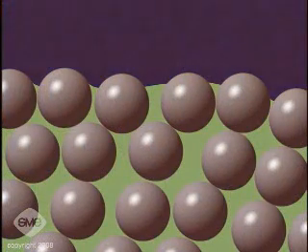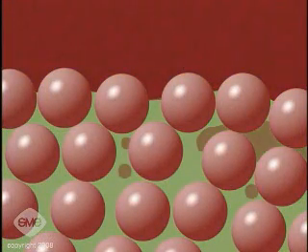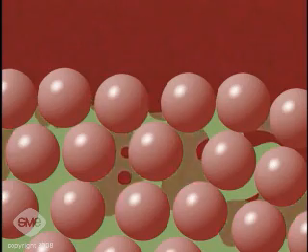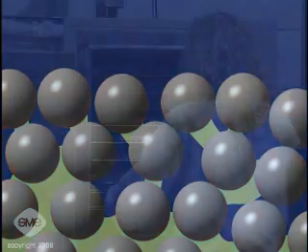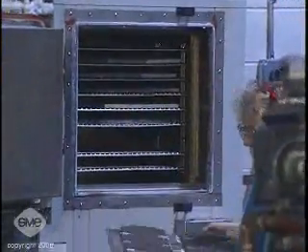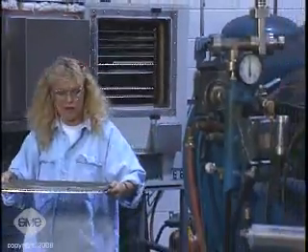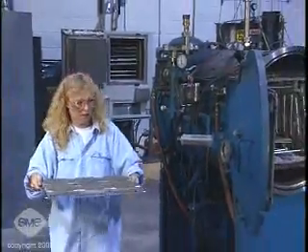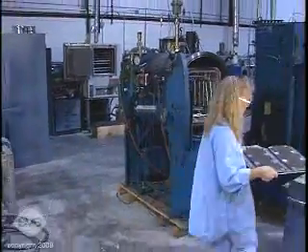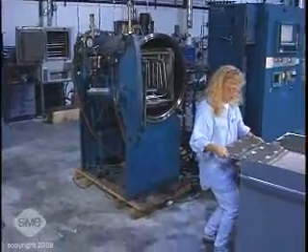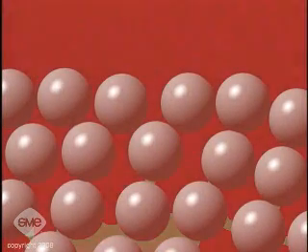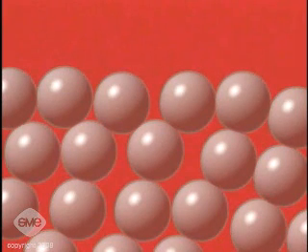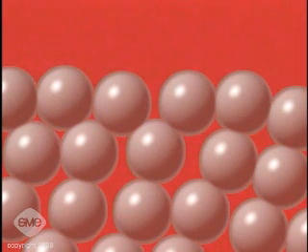Debinding is the process of removing the binder and can be by solvent extraction and heat or by evaporation. Either way, some binder is purposely retained in the part to maintain some green strength for subsequent handling. Sintering follows in a two-stage furnace. In the first stage, the remaining binder is removed at an elevated temperature. In the second stage, the part is sintered.